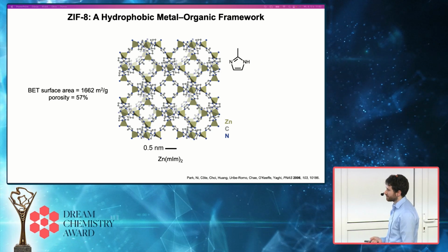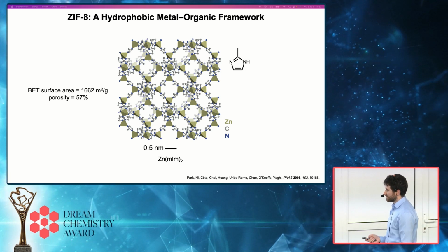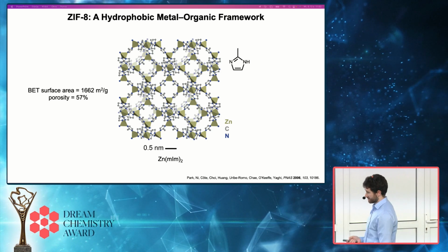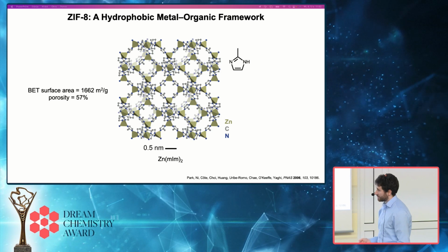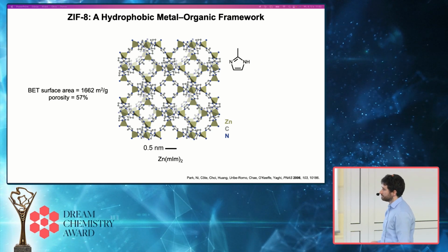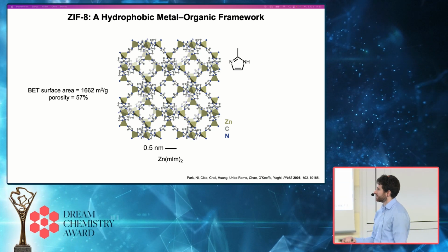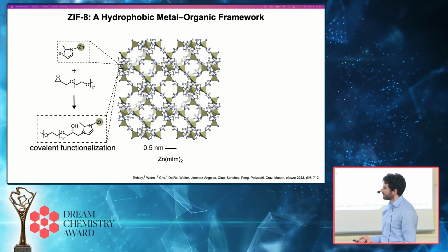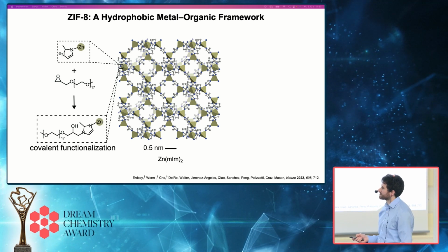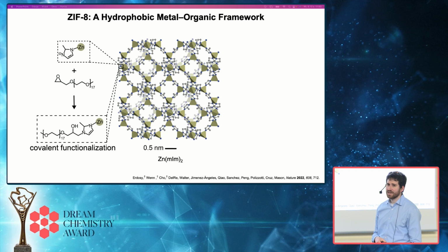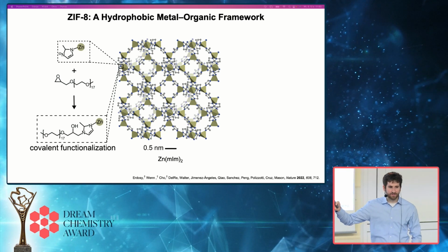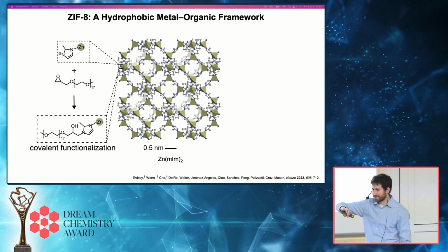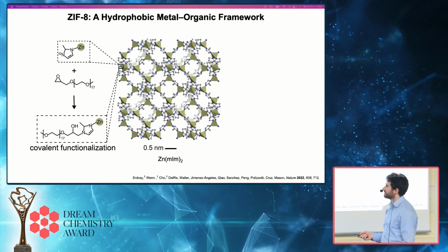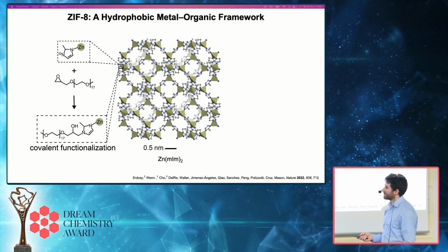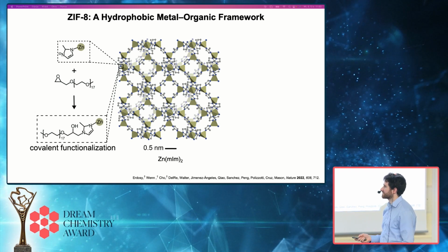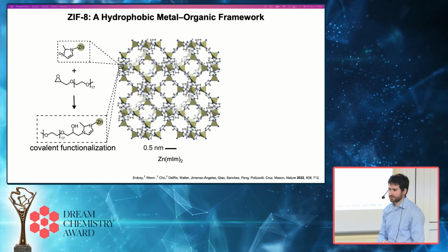In this particular case, this is a zinc or cobalt-based MOF that contains 2-methylimidazole as the bridging organic ligand. It has a structure very similar, actually, to some zeolites. Quite porous, has a really high surface area. We developed a new kind of covalent strategy for functionalizing its external surface with ethylene glycol-like oligomers that takes advantage of the fact that we believe there's 2-methylimidazolate ligands present on the external surface of this material that are not present because they're bridging on the inside of the material. And these are basically reactive handles that are capable of ring-opening epoxides and allowing us to selectively functionalize this external surface and make it very hydrophilic.